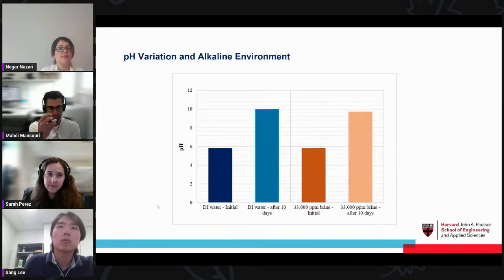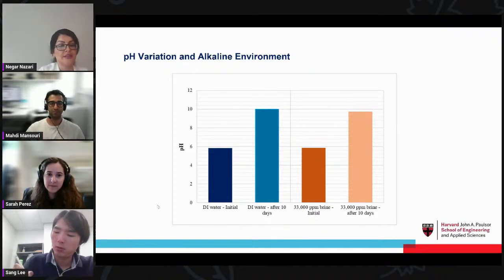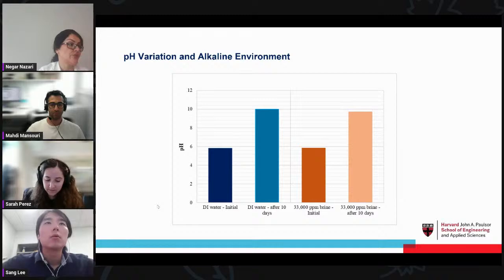So when we reacted the samples with the water, we checked the composition of the water after 10 days. We saw a very huge increase in the pH of the solution. The pH of the solution that we started with, for both the DI water and the brine solution, the initial pH was less than 6.